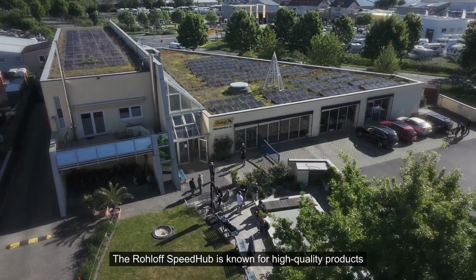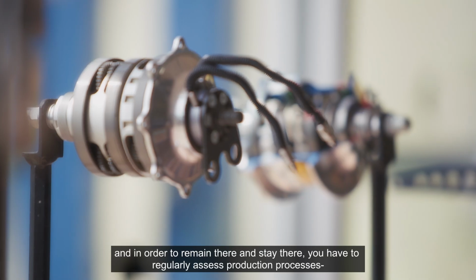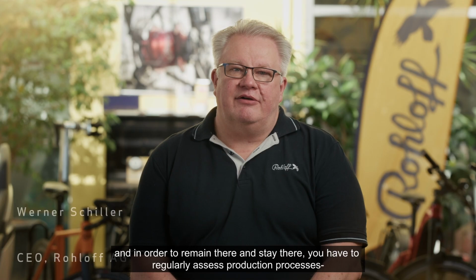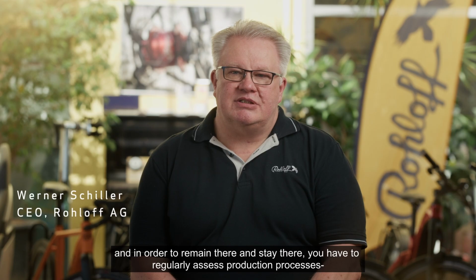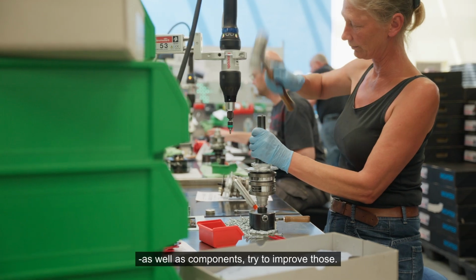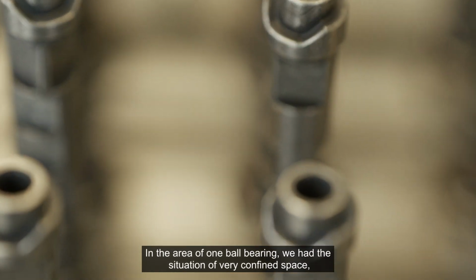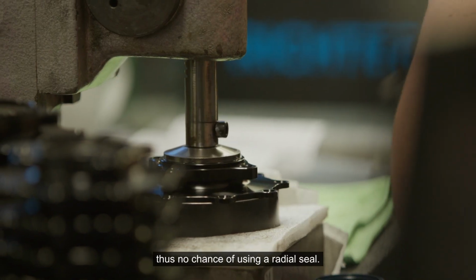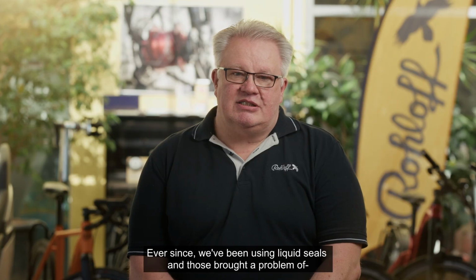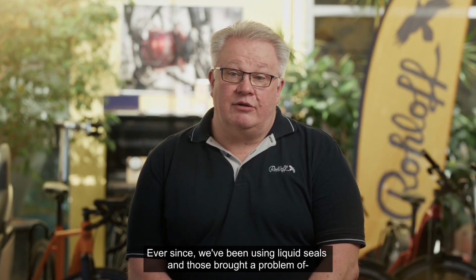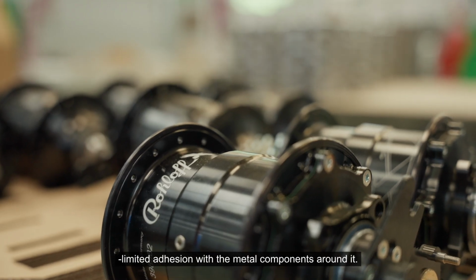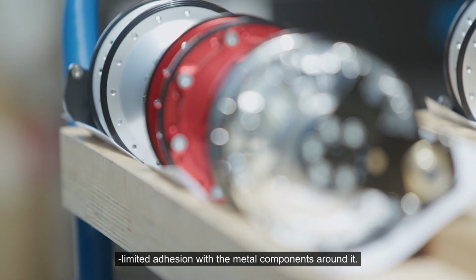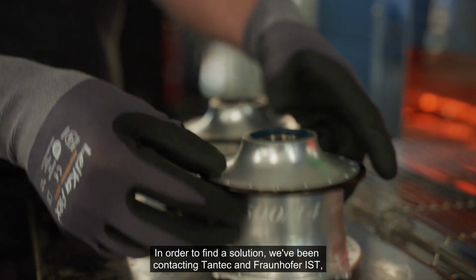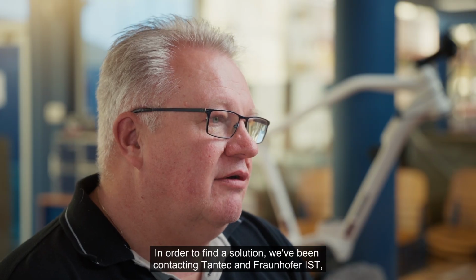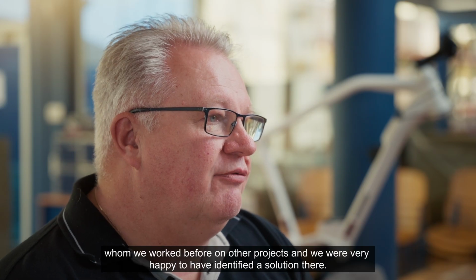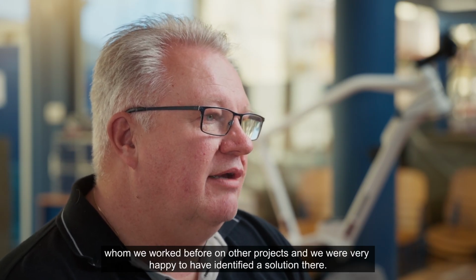The Rohloff Speed Hub is known for high quality products, and in order to remain there and stay there, you have to regularly assess production processes as well as components, try to improve those. In the area of one ball bearing, we had the situation of very confined space, thus no chance of using a radial seal. Ever since, we've been using liquid seals, and those brought the problem of limited adhesion with metal components around it. In order to find a solution, we've been contacting Tantec and Fraunhofer IST, whom we worked with before on other projects, and we were very happy to have identified a solution there.